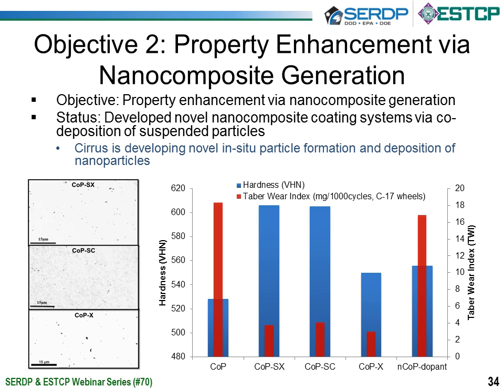So the second objective that we looked at was enhancing the properties, or mainly the wear resistance, through the incorporation of various hard phase composite particles. So again, we did this using two methods. One was just the conventional way of putting particles into the solution and co-depositing the hard phase particles, and the other was through the use of the Cirrus dopant. So we were successful in co-depositing various particles. I believe we looked at a number of different particles and a number of different particle sizes. And what we saw, the graphs here show both the hardness as well as the abrasive wear resistance as measured from the Taber wear test.